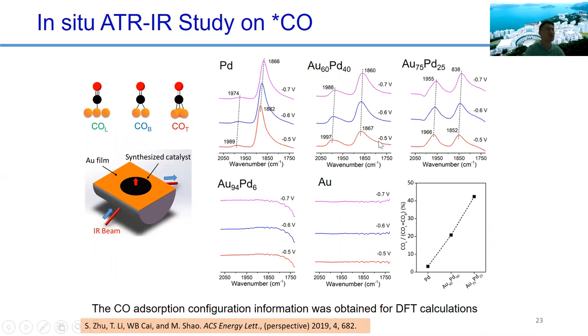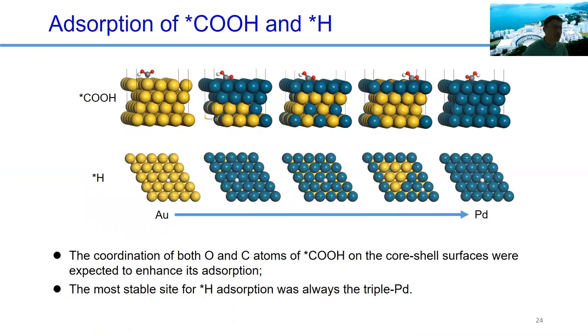We did a similar thing to check the CO binding configuration on different surfaces. This is on palladium nanoparticles, this is on gold palladium with 60% gold, 40% palladium, and this is 75% gold, 25% palladium, and others. You can see that the percentage of the linear or top-bonded CO actually increased, following this trend. So it can be explained by the same reasons.